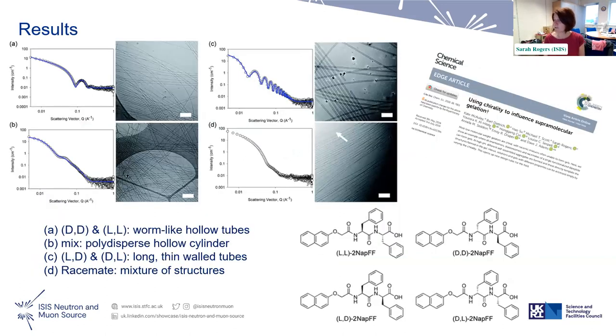So here's some results from a recent paper from the guys up at Glasgow. This is Dave Adams. So here they were playing tricks with this molecule called 2-NAPFF. And it has different stereo forms. So you've got LL, DD, LD, and DL, and they're shown there on the bottom right. And just changing that stereochemistry totally changes the scattering and the structures that are formed by those different gels. And you look at it as a gel, and some were soft, some were hard, and they couldn't quite work out what was happening there.